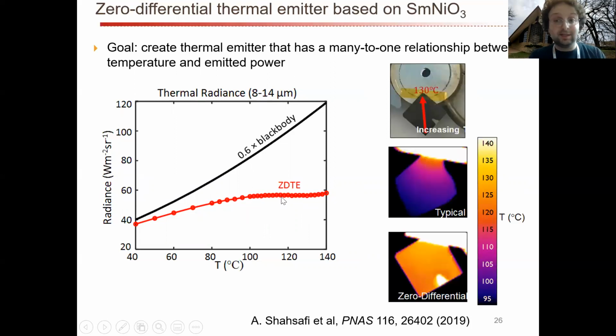And so we did some experiments with infrared cameras to show this. They're kind of fun. So we took a sample, we mounted it with Kapton tape on a heater. So there was a temperature distribution here. If you have a typical sample, for example, this is a piece of sapphire, you see that it's hotter over here, colder over here, and there's a gradient. However, if you put in our zero differential thermal emitter, you see that there's no apparent gradient. There is a gradient in temperature, but you can't see it because there's also a gradient in emissivity that cancels out the gradient in temperature as far as the infrared camera is concerned.